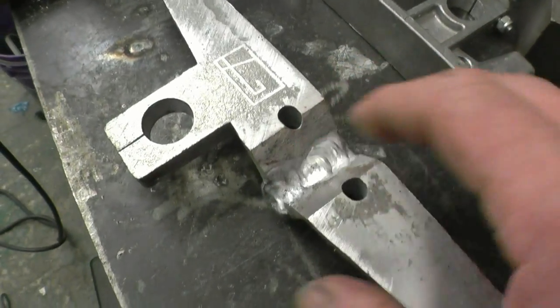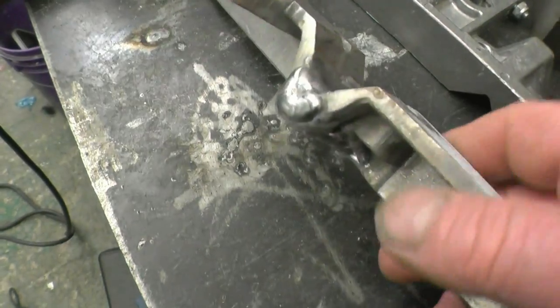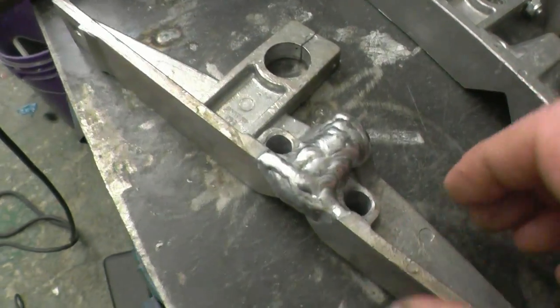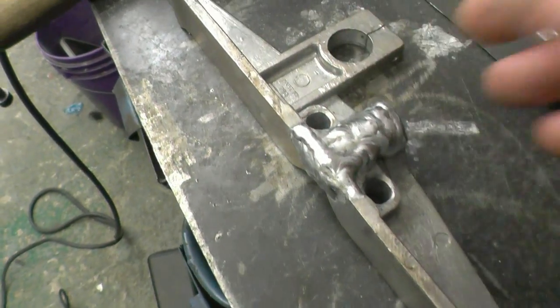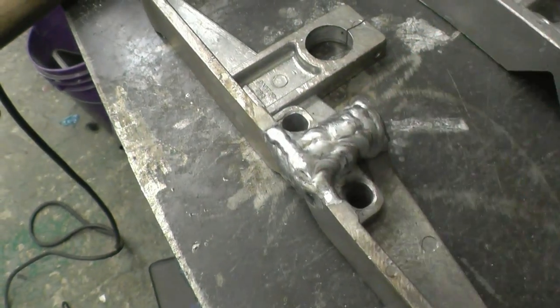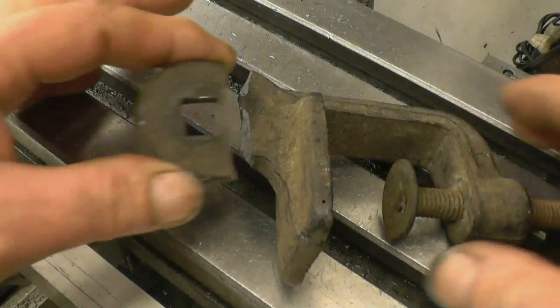This can be cleaned out with a file in here, but that's a decent repair. 100% penetration weld all the way through, built up quite nicely.